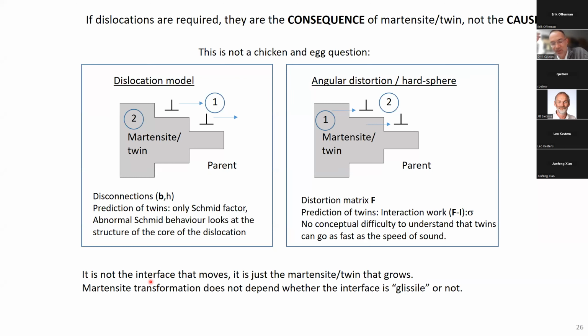If you adopt this point of view, you will not see martensite as it is written in textbooks. You will not see that the martensite results from an interface that should move. And you will not understand some sentences telling that to get a martensitic transformation, the interface should necessarily be glissile. Well, if you adopt this point of view, you don't care about the interface, actually, whether it's glissile or not. Actually, sometimes you do not even need dislocations.